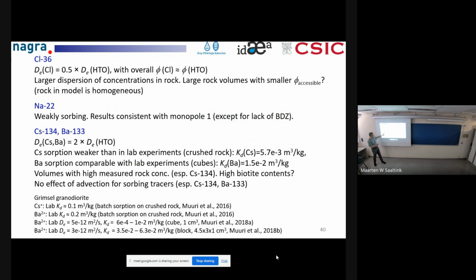But in the case of barium, we also did experiments not just with very finely crushed rock, but also with cubes, some of them centimeter cubes, and some others a bit larger, and then we get more or less the same values. So if you do experiments with very finely ground rock, with very small grain size, you have a lot of surface, so you have larger sorption. But if you do the experiment with small cubes, even centimetric size, then we have more or less the same KDs. So not all the surfaces are available in those cubes, and it's the same situation that we have in the intact rock that we model. So we have a good agreement with those measurements. I think that's also.